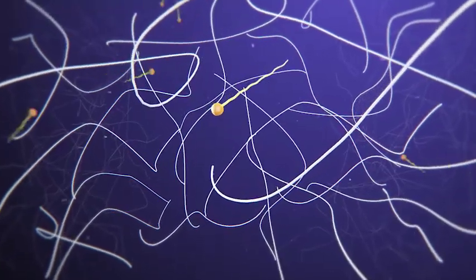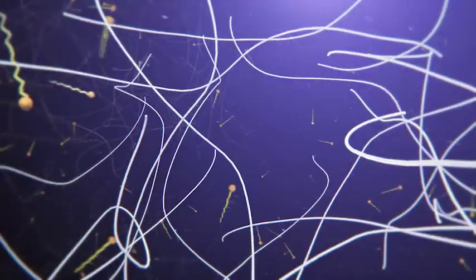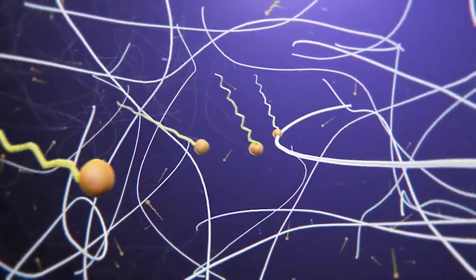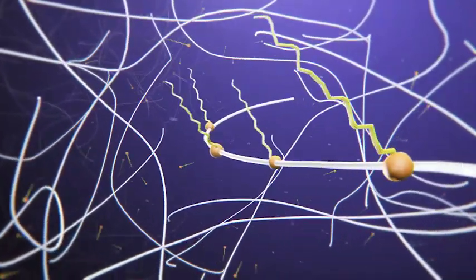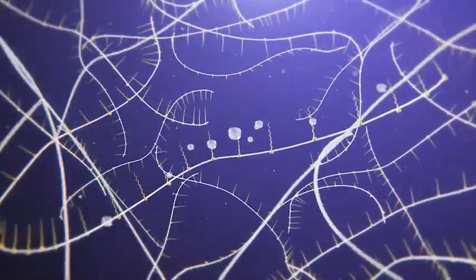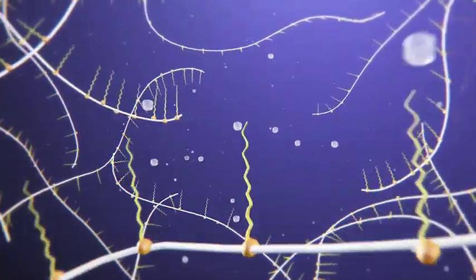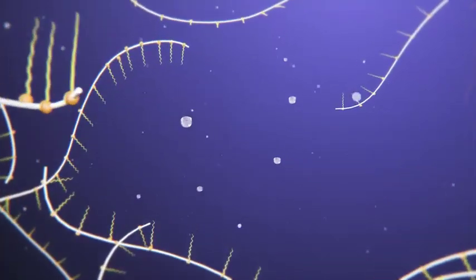Unlike Pall's polymeric coalescers, conventional glass fiber coalescers are known to absorb surfactants, progressively coating the fibers. When the small water drops approach the disarmed glass fibers, they are repelled, and no coalescing occurs.